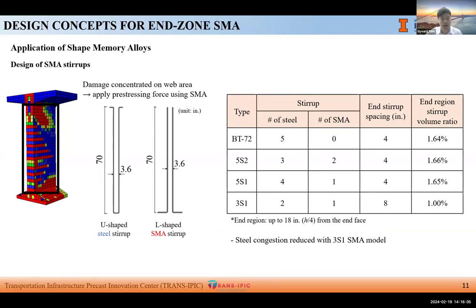5S1 also had 5 end stirrups, but with only a single SMA stirrup. The volume ratio was 1.65%. And lastly, 3S1 had 3 end stirrups with only 1 SMA stirrup with volume ratio of 1.0%. We can see that from 5S2 to 3S1, the volume ratio is decreasing with less amount of end stirrups.